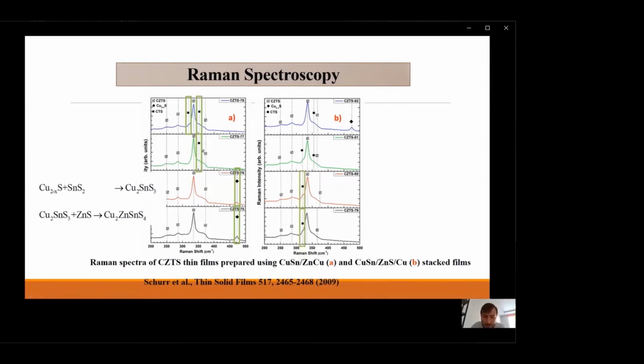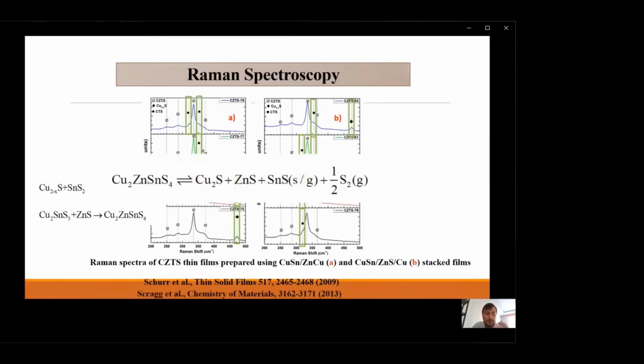In the B-type CZTS samples, you can see the copper sulfide is not observed, but the CTS phase occurs in all samples. Apart from these, in the sample at 575, you can see additionally a copper sulfide phase. According to Scragg et al., the formation of copper sulfide may signal a decomposition reaction in CZTS compounds. So 550 maybe is much better, or maybe you should limit the temperature to this temperature.